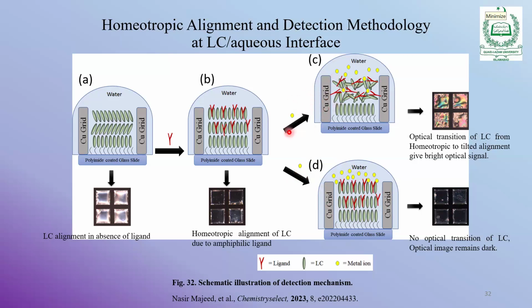If it interacts with it, it will disturb the arrangement of the liquid crystal molecules, and now they are not homeotropic. They are showing you the tilted alignment. So in different directions, the molecules are tilted. And from the dark texture, you are getting the bright image. Again, the liquid crystal is showing you the threads and bright colored texture. So it means that in the first case, when the mercury interacts with this amphiphilic molecule, it forms some complex with the amphiphilic molecule, and the liquid crystal arrangement is disturbed, and you get this type of response.